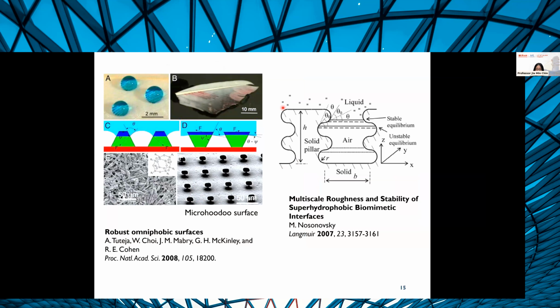And the reason for this is explained here in this diagram. So let's say you have a structure with these pillars with these etched microgrooves and a certain curvature. In this case, let's say you have a liquid layer here. You've got your solid pillars and you've got some air in this gap. And let's say this solid line here is the liquid-air interface. And this point represents the liquid-solid-air contact line. So for this liquid to wet a surface with these micropillars, that liquid needs to penetrate further into this gap. But that requires a temporary increase in the contact angle of this liquid. And that is energetically disfavored. So what you're doing here is that by creating this special morphology, you're creating an energetic barrier, a local energy minimum, to stabilize this state whereby even hydrocarbons can be repelled by this surface.